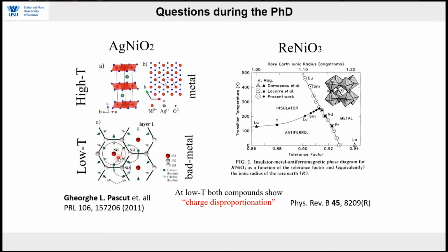The one which is correlated has a local moment. The one which is not correlated has zero local moment. So with these results, basically what I'm concluding is that when people say that you have charge order based on experiments like resonant X-ray scattering, you have to look a little bit carefully, because you don't really have charge order, but each site can behave differently. And I'll show you at the end of this talk that I went into other materials where people claim that you have charge order, and what I showed is that in those materials, in reality, different ions have different electronic properties.